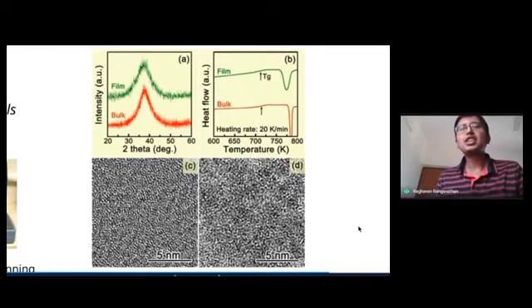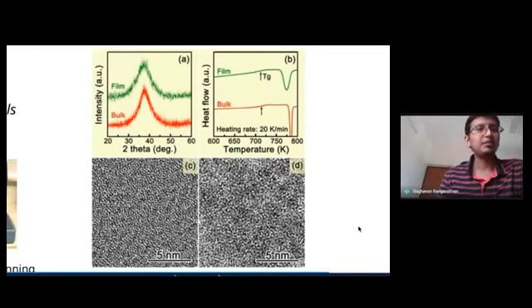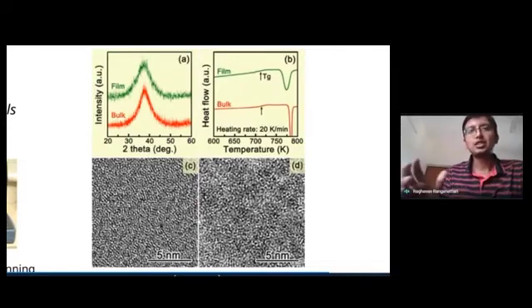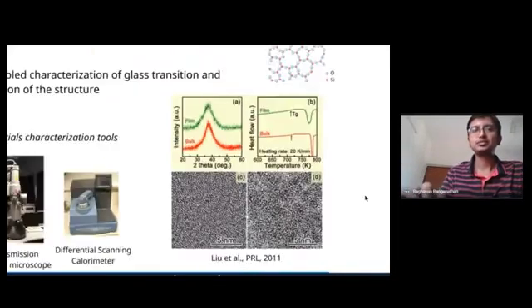But perhaps the most interesting characterization tool is the employing of high-resolution electron microscopy. So the pictures that you see on the bottom panel are very high-resolution images of a glass, where you can see the individual arrangement of these atomic units. So all these are representative of the short-range order, but you can clearly see the lack of long-range order in these structures.